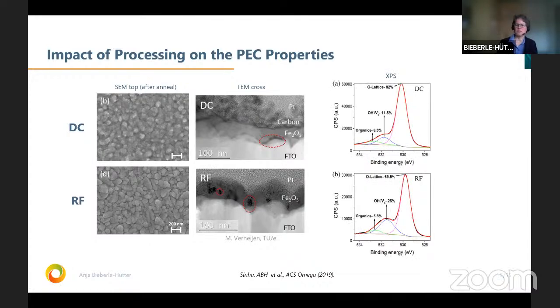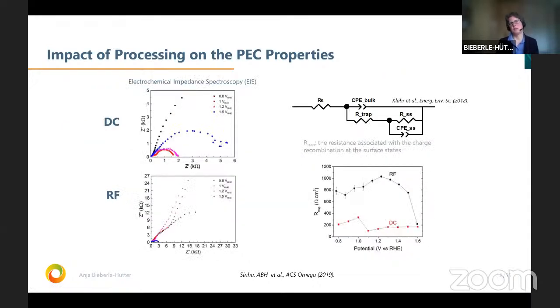We also see some differences in the XPS data. So this is the XPS data of the oxygen. And the main difference is here around this 532 electron volt. You see here a higher bump or a higher peak here. So with the RF samples, we get more OH minus or oxygen vacancies. So this gives us quite an image about what is the structure and the chemistry of these samples.